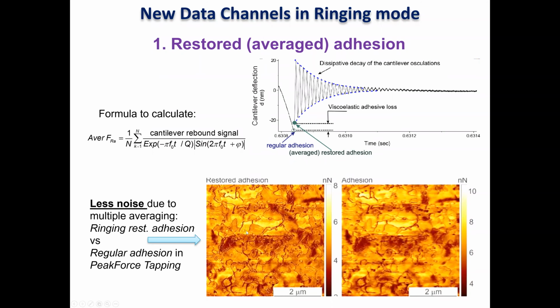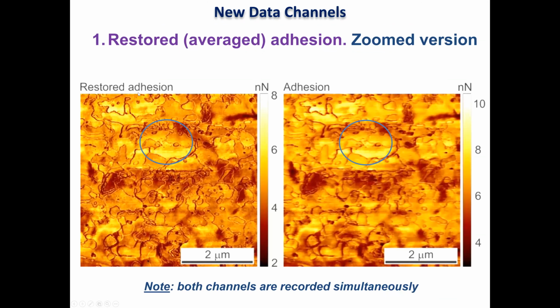the same time. By the way, that's an important part. All these channels that I listed can be measured at the same time. They all measure simultaneously. So just to give you a bigger view, this is restored adhesion, this is regular adhesion. You can see the difference. For example, these spots are very nicely seen here and barely seen here. So resolution is better because the signal-to-noise is now much better.